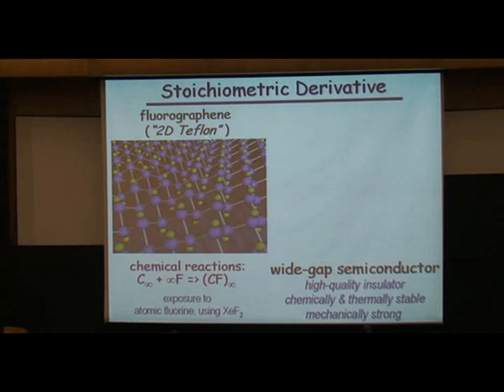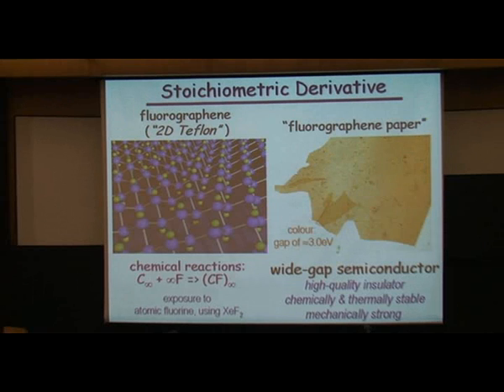So what we get here is a stoichiometric derivative of graphene, which we call fluorographene. You can consider it as a two-dimensional Teflon, because the formula is the same, and this is how, if you make many layers, we call it fluorographene paper, you can really see that this material, unlike graphene, is completely transparent, even if you stack plenty of those, and the color corresponds to the gap I described before, 3 eV.